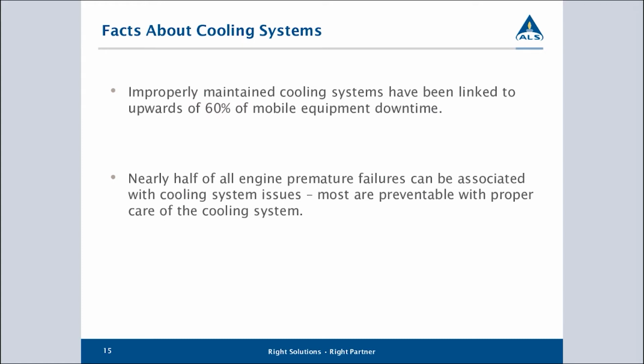A number of research bodies have looked into what causes failures on engines, and most of these conclude that at least half of engine failures can be attributed back to the coolant. And in my personal experience, I've seen it probably rated even higher than that. Often we'll have an engine that has failed, possibly it's failed a bearing, for example, but when we strip the engine down and examine it, we'll tend to find that there was in fact a corrosive problem in the cooling system that allowed coolant to leak into the engine oil, which had ultimately caused the bearing failure. So the origin of the failure was through a poorly maintained cooling system.